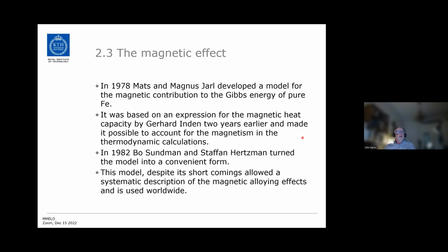The magnetic effect. Magnus Jarl and Mats developed a model for the magnetic contribution to the Gibbs energy of pure iron. And that was based on an expression for the magnetic part of the heat capacity, which had been suggested by Gerhard Inden a couple of years earlier, which made it possible to account for the magnetism in thermodynamic calculations. But it was not until 1982 that Bo Sundman and Staffan Hertzman turned this model into a more convenient form. And it has many shortcomings, but despite the shortcomings, it allowed a systematic description of the magnetic alloying effects and is used worldwide.